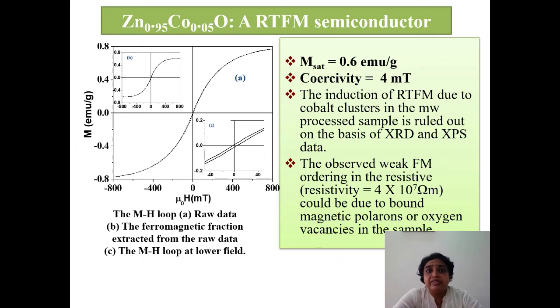These materials have tremendous application in spintronics. So we synthesized zinc oxide doped with cobalt, and we found room temperature induced ferromagnetism in this zinc oxide doped with cobalt. This is VSM data which shows a very small coercivity field, that is 4 millitesla, and a very good value of saturation magnetization, that is 0.6 emu per gram.